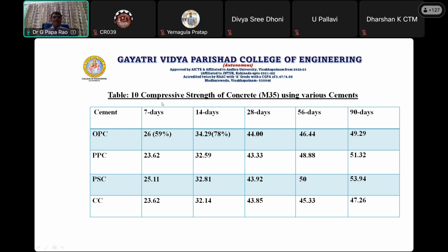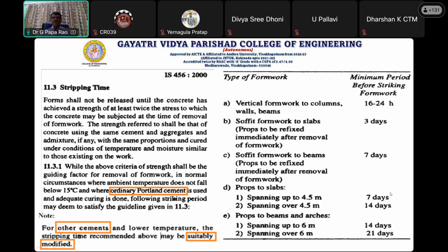Here our focus is to arrive at the stripping time of the blended cements, because IS 456 speaks about stripping time only for OPC. Therefore, we need to arrive at the stripping time for the other blended cements. At 7 days we got OPC 26 MPa, 14 days 34, and 28 days 44. We estimated the percentage strength of OPC with respect to 28 days: 26 by 44 gives 59%. Again, our OPC M35 grade concrete got 78% at 14 days and 59% at 7 days. We have focused on 7 days and 14 days, the stripping times as per IS 456.